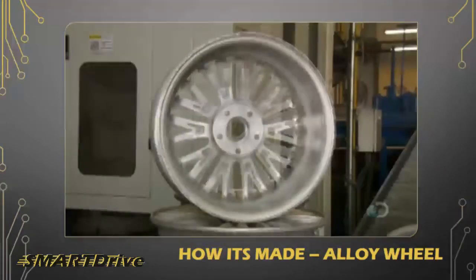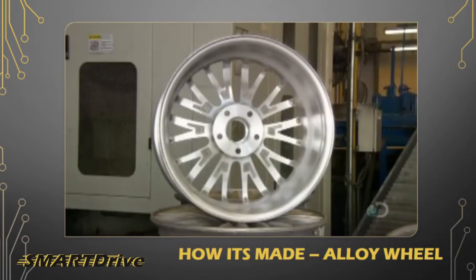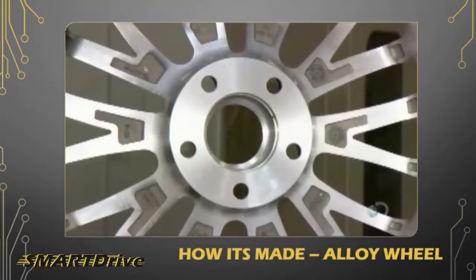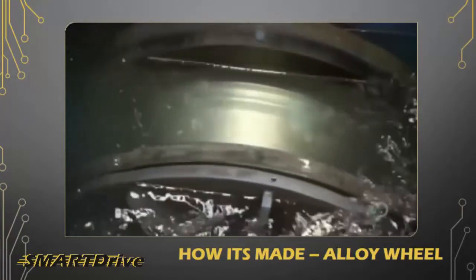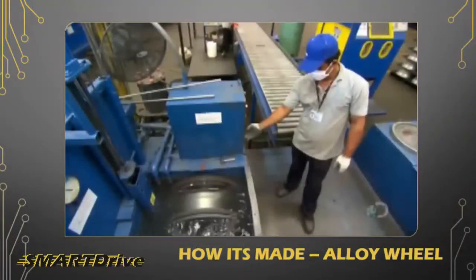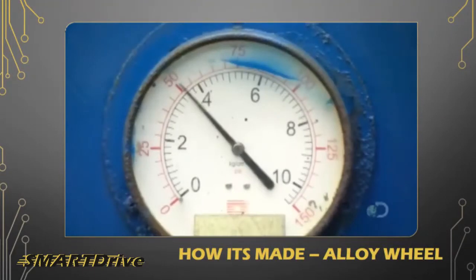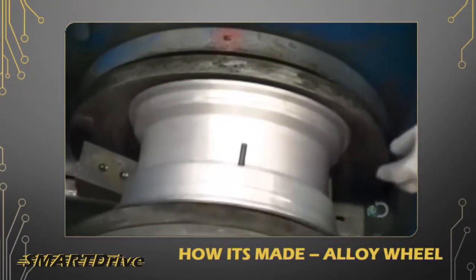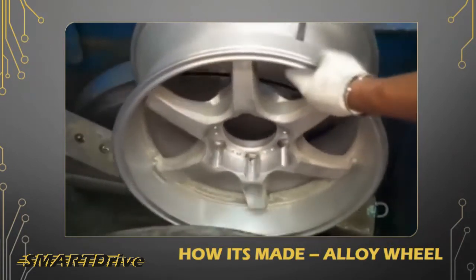The shape now finalized, it's time to test the wheel to make sure it's airtight. While pumping air into the wheel, they submerge it in water. Should any air bubbles appear, it would mean there's a pinhole in the metal or some shrinkage, in which case the wheel would fail inspection. No air bubbles? The wheel proceeds to the automated painting line.